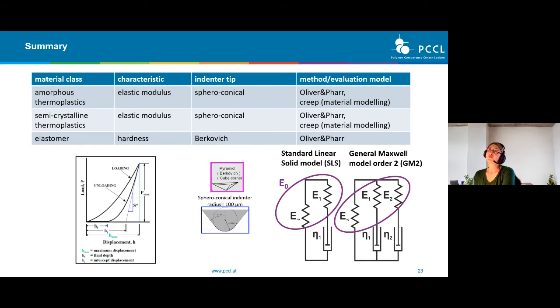If we want to measure the hardness on an elastomer, I would recommend using a Berkovich indenter because it has a more defined and precise geometry. When we measure hardness, we are dealing with imprints, and therefore the Berkovich, I think, is a better choice. Here we also use the Oliver and Pharr method for hardness measurement.